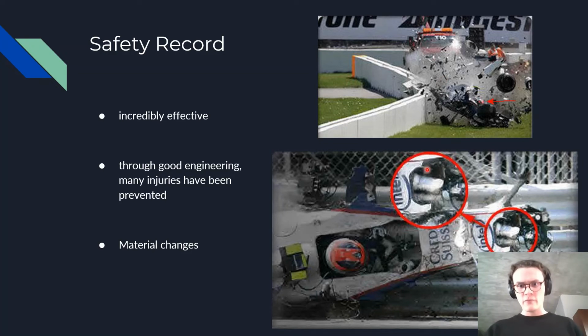I put a few pictures here of a crash in 2007 that Robert Kubica had. You can see the car gets obliterated after it hit the wall at 300 kilometers an hour. But down here you can see the monocoque, and it's just fine. You can see here at the front, his feet are well protected still. The front totally broke away, which is the crash structure that we talk about later. But he himself is protected fully, and he did not get injured here at all. Even though this is a really scary crash that had G loading of up to 75 Gs, he was ready to go 2 races later.